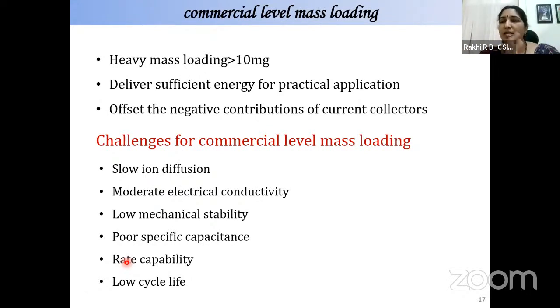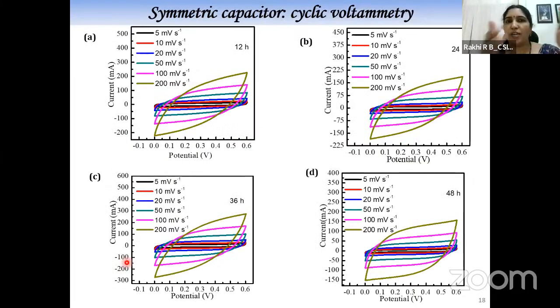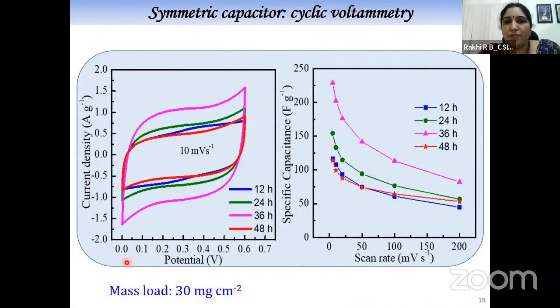So let's see with our material whether we are able to overcome this. We fabricated a symmetric supercapacitor with the 12-hour sample, 24-hour sample, 36-hour sample, and 48-hour sample, all directly grown on the nickel foam substrate. We are just pasting it, and with the help of electrolyte and taking the connection out, we test. We found that with a mass loading of 30 milligram per centimeter square, it gave a specific capacitance near 250 farad per gram. That is a lab scale testing conventional device. Whatever it is giving, that much capacitance we could obtain with this much high mass loading.